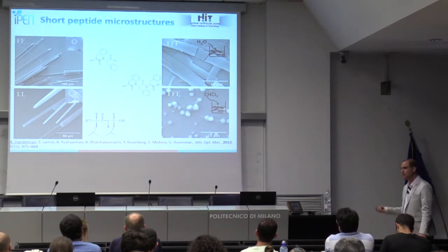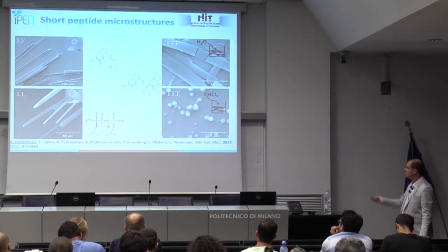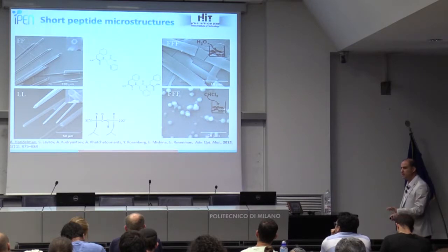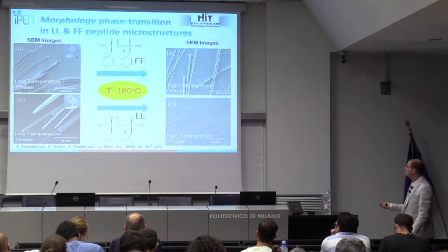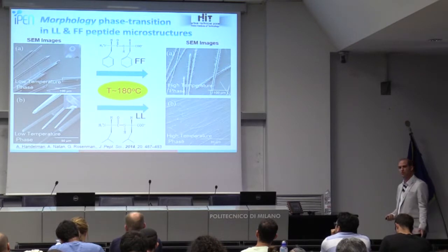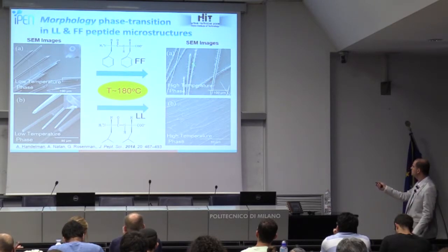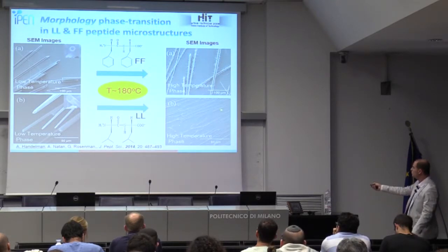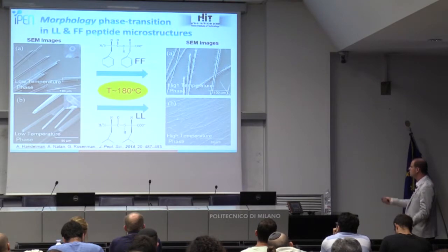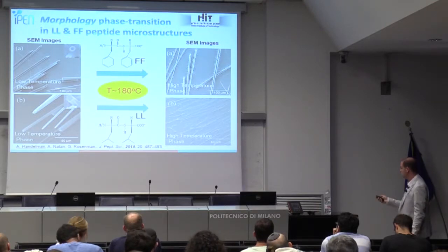And there is another one, dileucine, which is another amino acid that we investigated, also very similar to the diphenylalanine. As you can see here, it doesn't have any aromatic ring, which is the carbon that you see here. So we characterized their morphology, and then we noticed that if you heat these kinds of peptides at a high temperature, they change. You see here there are all kinds of hairs: the microtubes of the dileucine change to all kinds of very long and very thin tubes, nanotubes. So from micro they turn to nanotubes.